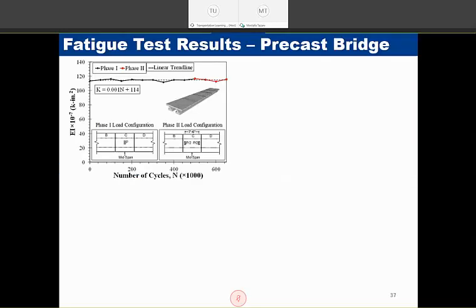So let's talk about test results for these bridges. This graph that you can see in this slide shows the number of fatigue load cycles that we applied, from 0 to 600,000, and the vertical axis is the effective stiffness of the bridge. You can see that when we started the testing for the fully precast bridge and when we ended, the overall stiffness of the bridge didn't change much, so we could tell that all of the joints of the bridge are structurally viable for basically more than 100 years of service life.